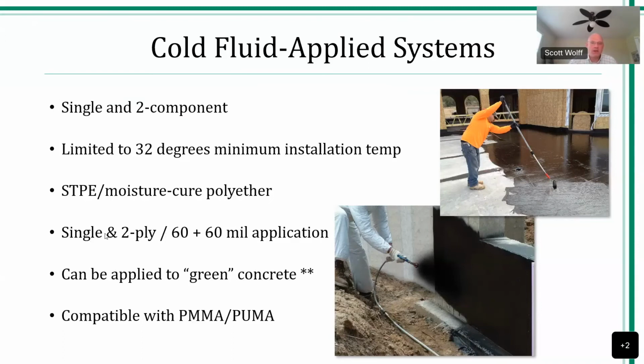And we can apply a single ply or 2-ply reinforced, 60 mil plus 60 mils with reinforcing fabric. One of their biggest benefits, however, is application to green concrete. The moisture curing aspect of these cold fluid applied membranes actually benefit from and frankly require atmospheric moisture and substrate moisture to go through their curing process.